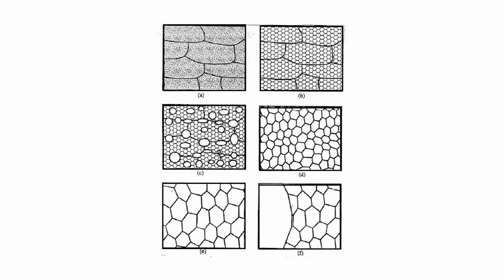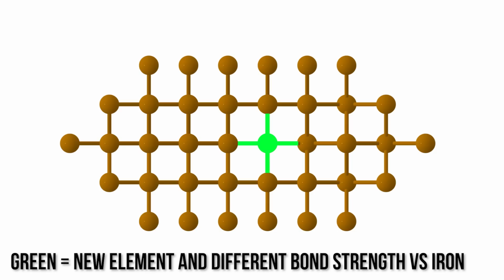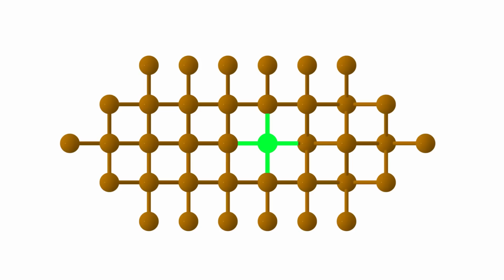Now in the heat treating of steel, we are able to rearrange the overall structure of the steel, which we call the grain structure. But that is a very different thing to changing the strength between the iron atoms. And that is what needs to be changed to change the stiffness of the steel. When we add other elements, the strength between those bonds are going to be different, and that's why we see a change in modulus when we have other elements alloyed in. But because most of it remains iron atoms and only a small percentage of other stuff is usually alloyed in, is why we see the Young's modulus remain between 190 and 210.